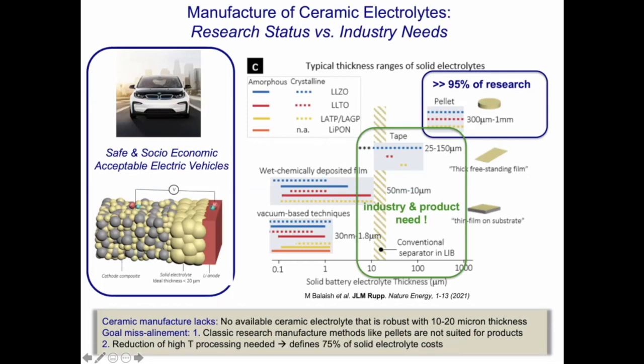So I want to just highlight real quick where industry is and where research is. When I analyze the field and what they are doing in ceramic manufacturing, we made this plot with the team, with my colleague Moran Balaish and many other colleagues. First of all, the good news is that most of the chemistries can already be processed either in thin film structures, keeping oxidation in check, or as tapes or pellets as ceramics. However, what is a bit of a challenge is that 95% of the published research for lithium garnet is mostly done on pellets.